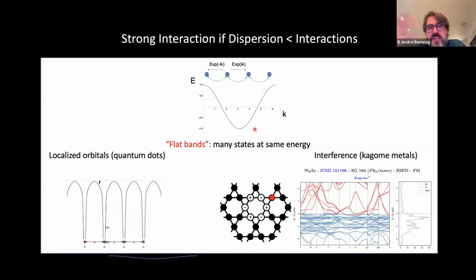But if the kinetic energy is much larger than the interactions, then we basically don't care, because the kinetic energy of electron 1 adds up to the kinetic energy of electron 2. In terms of kinetic energies, it's a very simple problem. It's just additive. When I add interactions, then the electrons start talking to each other, and this becomes an unsolvable problem. But if the kinetic energy is large, then interactions won't matter. So one way to make the interactions important is to make the kinetic energy small.